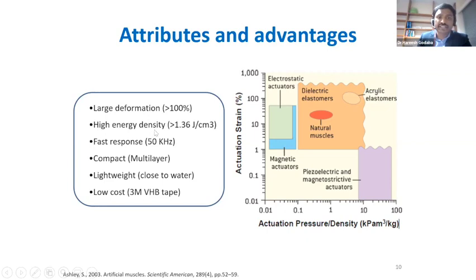And as I mentioned, the energy density is very high. The response speed is also relatively high compared to many actuators. They can go up to several kilohertz. You can also develop loudspeakers by using this type of artificial muscles. Then, because these are very thin films of elastomer, we can make compact multi-layer structures, which can help to increase the force outputs of this kind of actuators. And the density is close to that of water, so it's lightweight. And also we have a variety of natural and synthetic elastomers that we can use for these actuators. For example, natural rubber, and 3M's very high bonding double-sided adhesive tape is also a common material that's used to make these dielectric elastomer actuators.